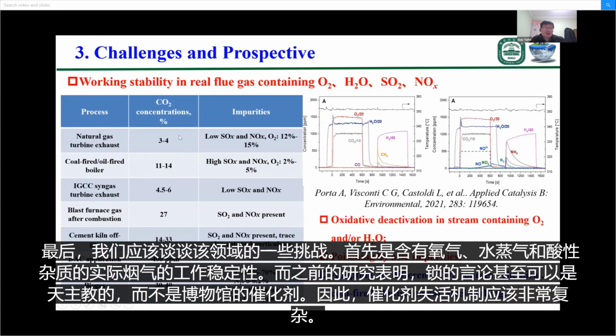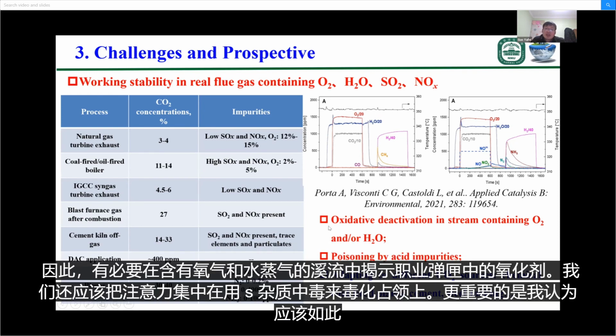And lastly, we should talk about some challenges in this field. The first is the working stability in real flue gas containing oxygen, water vapor, and acid impurities. And a previous work indicated that NOx species can even be catalytically converted into ammonia over the ruthenium catalyst. So the catalyst deactivation mechanism should be very complicated. Thus, it is desirable to reveal the oxidative deactivation mechanism in a stream containing oxygen and water vapor. Also, we should focus on the deactivation by poisoning by acid impurities.